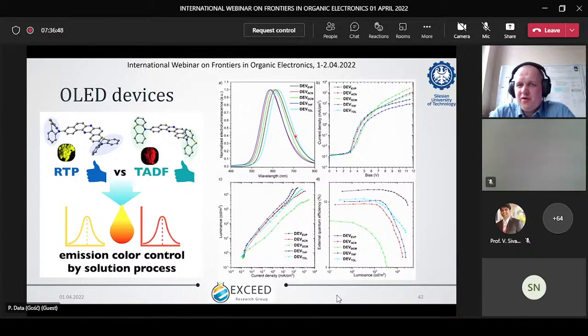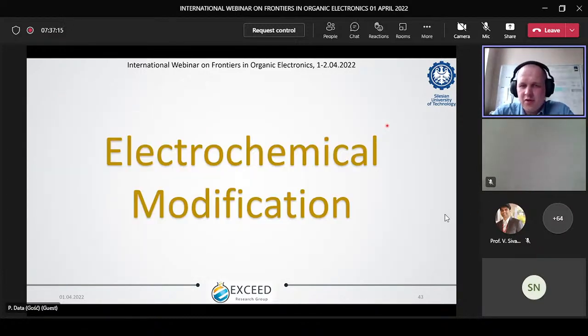Toluene formed very nice equatorial conformers and very nice efficient devices, and more polar solvents caused troubles, and we had more axial conformations and less efficient devices. But generally, we proved that by solution process, by changing the solvent, we can affect our final conformation. Another way to modify our emitters, and the way which I really like, is the electrochemical modification.